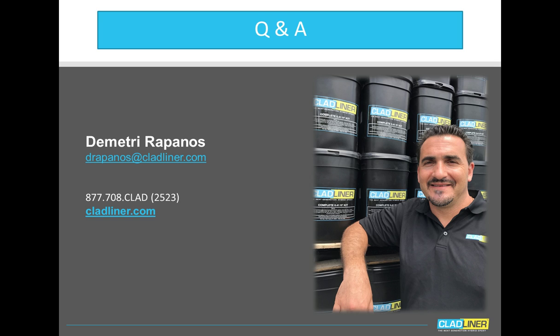As far as application goes, Cladliner can be applied in 2 ways. Number 1, for small applications where it makes sense, Cladliner can be applied directly out of the pail with a trowel onto the wall. Hand applied or hand transferred from the trowel onto the wall and trowel smooth. If larger structures or more volume is being achieved, as you saw in those pictures, a wet mortar spray pump can be used. The product would still be mixed up and then poured into the hopper or the auger, at which point it would be then transferred through the pump and sprayed to the wall. So the pump would then become the transfer mechanism to get the material to the wall, and then at that point it would probably be back-troweled to be smoothed down anyway.